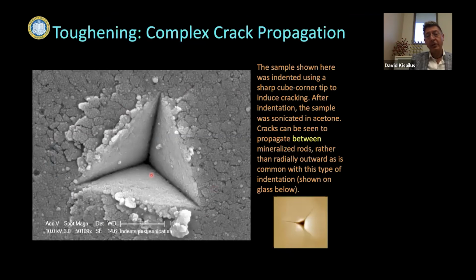Also, when we look closely at one of these nanoindentations, you can actually see that the cracks that have formed actually go around these nanorods. So this is a cross-sectional view of one of these nanoindentations. So the cracks are being deflected at these interfaces between the organic fibers and the mineral.